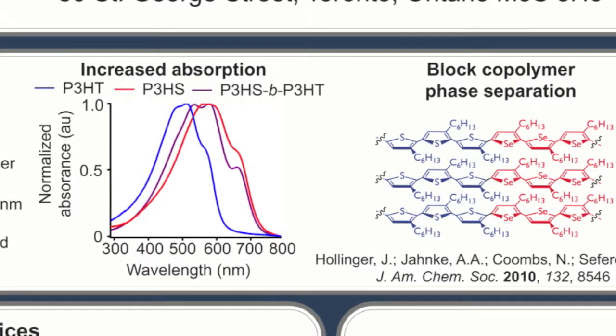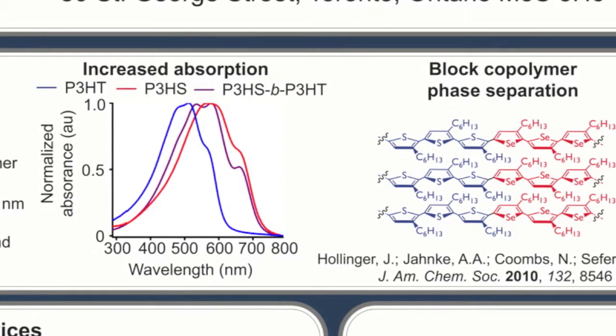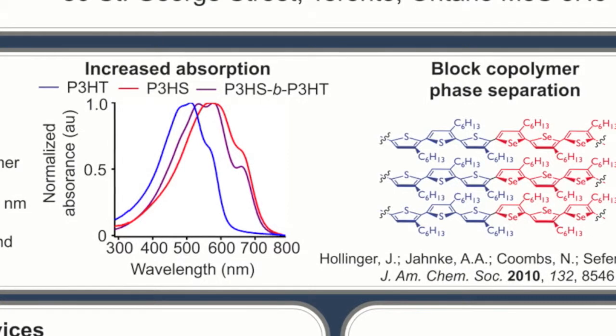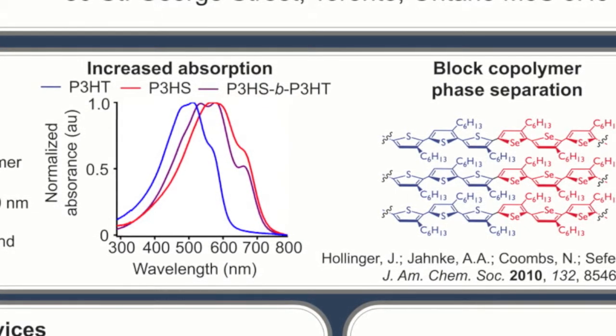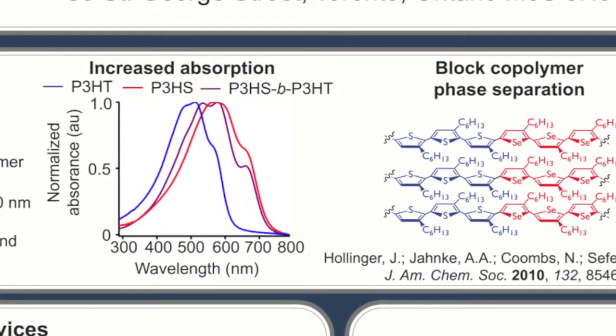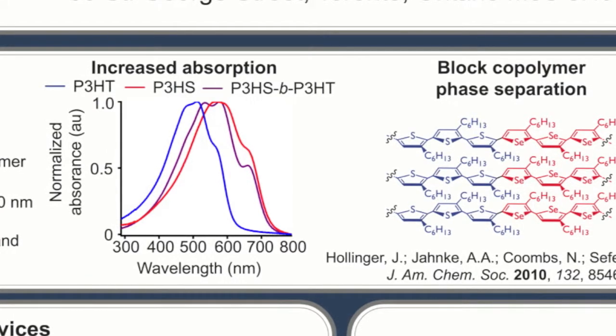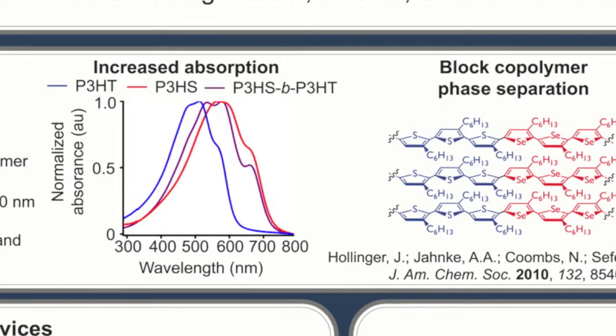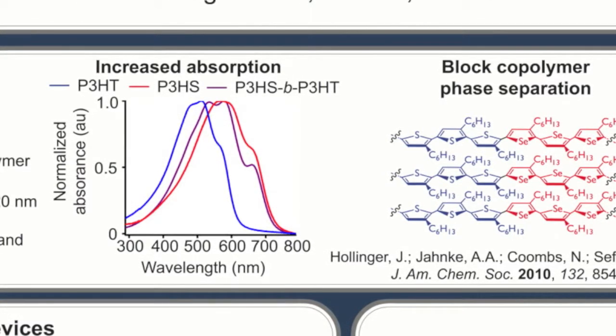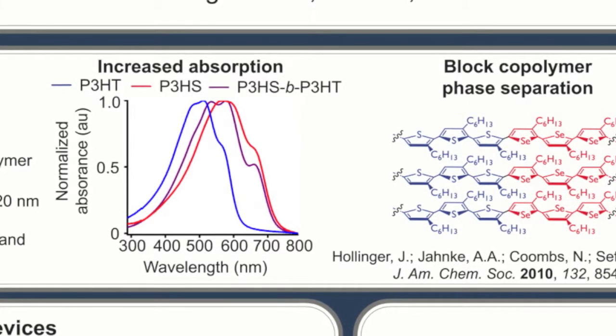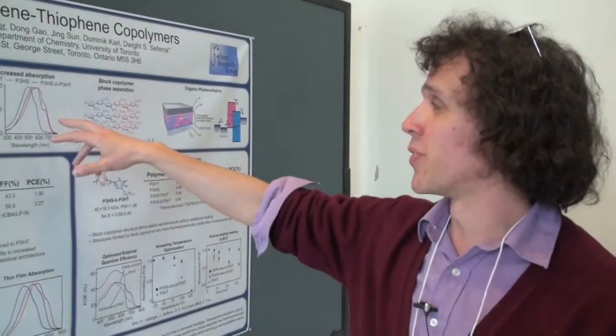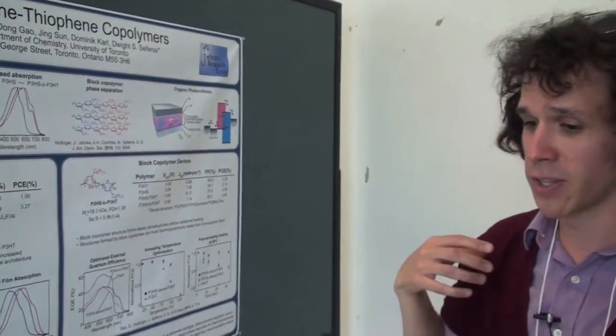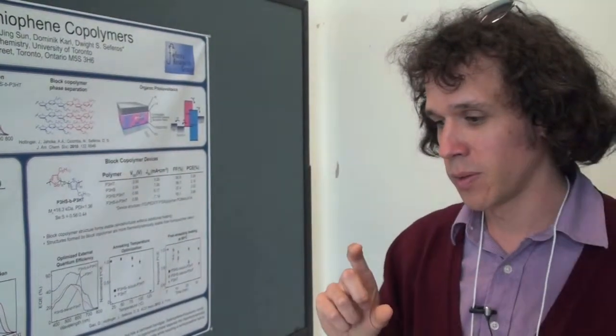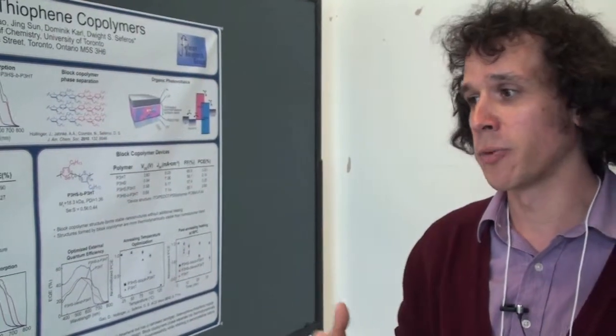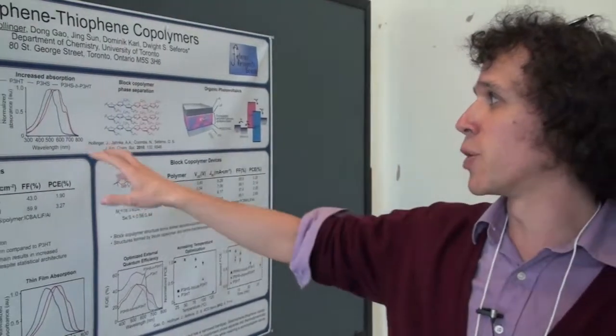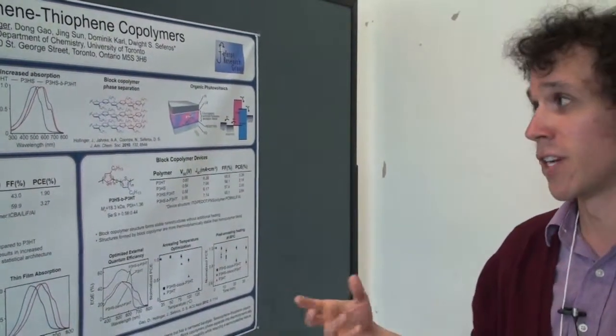The polythiophene is here in blue and the polyselenophene is in red. And if you make a block copolymer, you see that the absorption onset is matched with the polyselenophene homopolymer, indicating that the band gap is maintained from the pure selenophene phase. What was interesting to us was that we saw this vibronic fine structure in the form of a shoulder in the red wavelengths, which in the homopolymer is indicative of pi-pi stacking interactions. And what this suggested to us was that these polymers phase separated in the solid state, which is interesting because these phase separations happen on size scales that line up nicely with the exciton diffusion lengths of these cells. So this could not only optimize the absorption profile, but possibly also the morphology in order to increase the overall